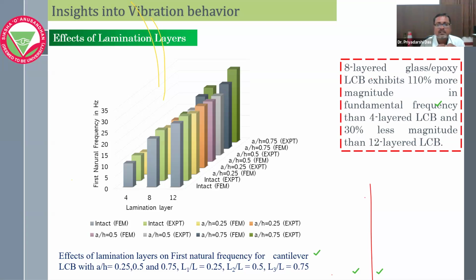But we have chosen the 8-layer lamination for our research, since we are doing it numerically as well as experimentally for ambient environment conditions. 8-layer sits well with us. That's why we have taken the 8-layer beam. So a 12-layer beam or 16-layer beam can be taken. A 20-layer beam also can be taken, but the curing process or the fabrication process itself will take much time.